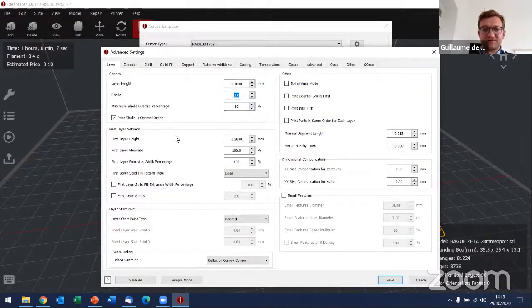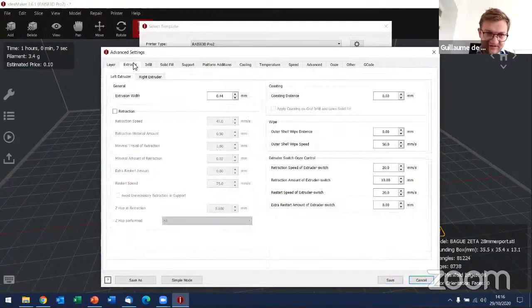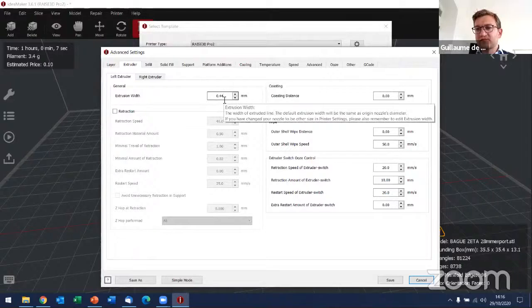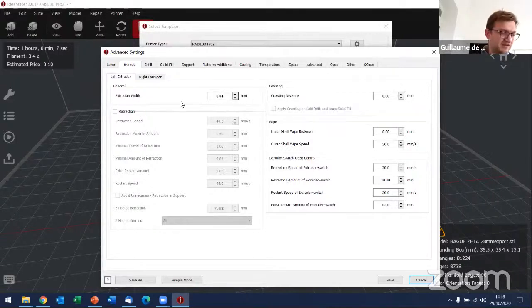That's for the first tab. That's really the 2 most important parameters. I'm not going to go too much in detail, so we're going to go directly to the second tab. Here you have 2 really very important parameters: extrusion width and retraction. Extrusion width is the exact pass size. So your nozzle at the moment is 0.4 millimeter. It could be another size. You could print with bigger or with lower, but for the moment we have a nozzle of that size. But you can decide to print a pass that is going to be slightly bigger or slightly lower. Usually with ceramic and metal filaments, we choose to extrude a little bit more than the size of the nozzle to increase adhesion.